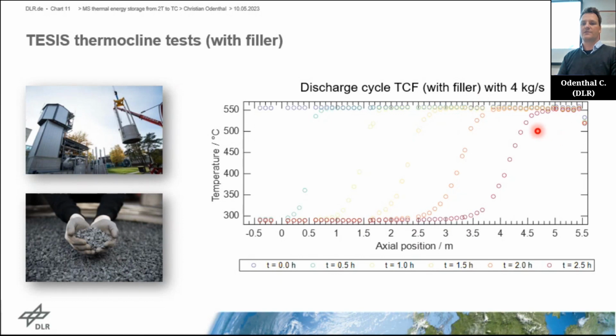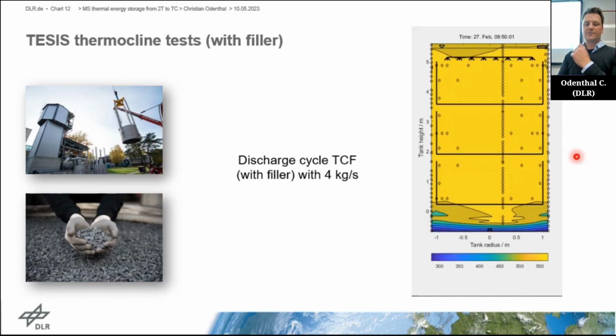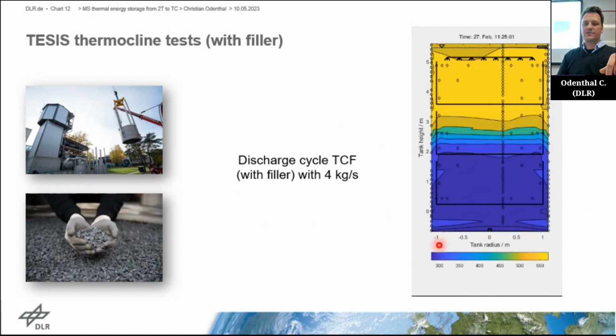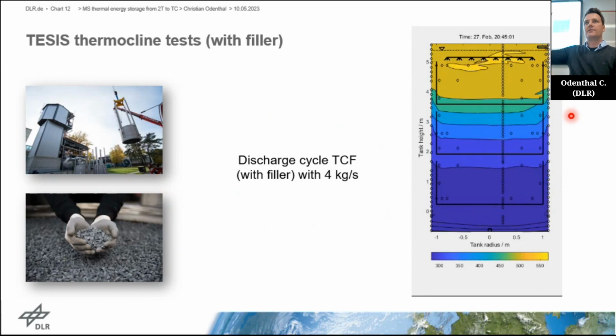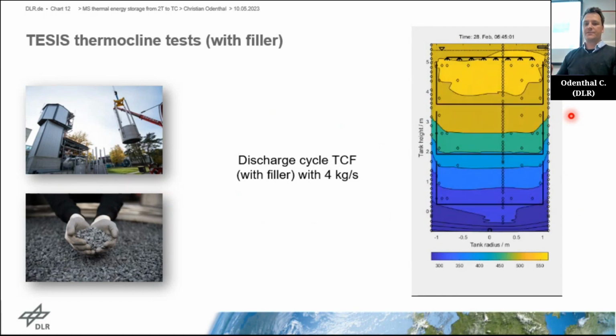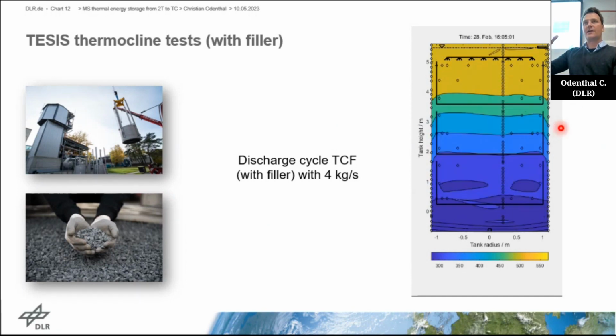One important aspect with this system is that during operation, due to the heat transfer, but also through conduction, this thermocline region is always expanding slowly. You can see that on the next slide. There's a small video we created from the actual measured temperatures. It's just an interpolation of the temperature measurements. It's not a simulation. I can start it. And then you can see, as you cycle through, or if you do cyclic operation, that your thermocline is slightly expanding with every cycle.